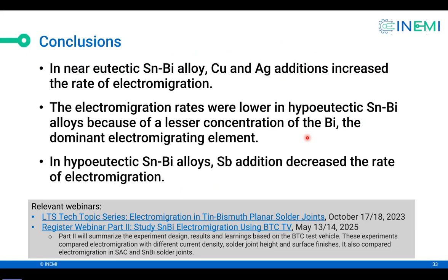So this is the conclusion, and I've already said these words in the previous slide, but I'll repeat it again. In near eutectic, copper and silver additions increase electromigration rates. In hypoeutectic, electromigration rates are lower, and addition of antimony decreases the electromigration rate in hypoeutectic solder even further.